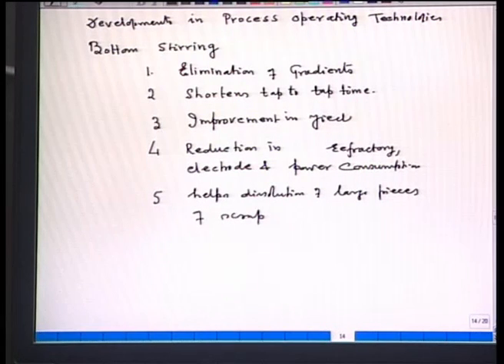Now, a very important thing is where these bottom stirring plugs are being introduced. For stirring purposes, one uses an inert gas like argon or nitrogen. If the steel can accept nitrogen, then nitrogen is the stirring gas. If the steel cannot accept nitrogen, then argon is the stirring gas. Now, common sense says if you have 3 electrodes, then the position of the 3 electrodes with respect to the bath is clear. Then the stirring plug should be put in between the electrodes.